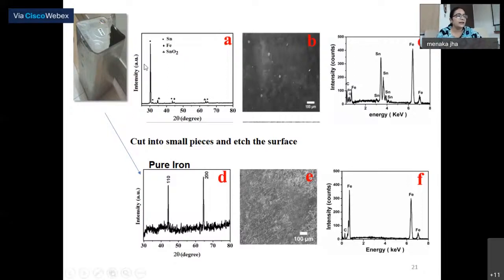I put this tin can under EDAX, and I found that it has a good quantity of tin, so tin is in large quantity. Then I ran X-ray on it, and I saw it has tin, iron, and tin oxide. On the surface you can see a little bit of tin oxide and iron. I wanted nano iron, which is a nano iron sheet, and here I tried to make it.